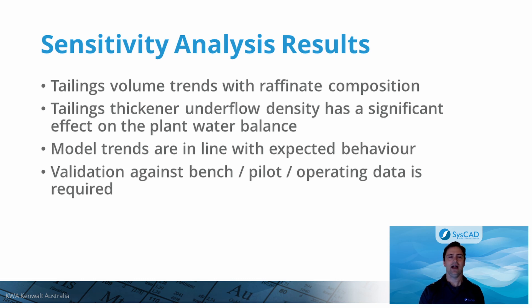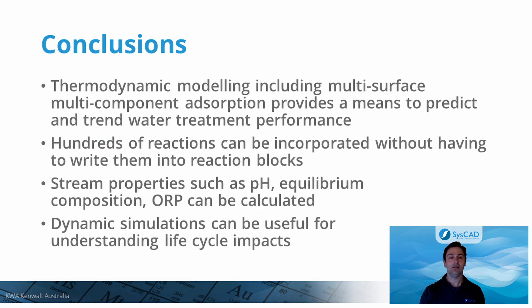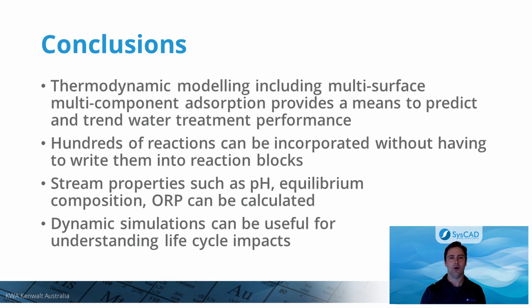This sensitivity analysis also demonstrates how SysCAD with TCE can quantify trending of effluent volume with raffinate concentration as well as run-of-mine tailing solids content. In every scenario tested, model trends were in line with expected behavior. That being said, use of this model or an adaptation of it would require validation against bench, pilot, or operating data prior to use for actual plant design. In conclusion, SysCAD combined with the TCE add-on provides a means to model very complex processes. The PHREEQC software package with an adapted version of the MINTEQ version 4 database was integrated into SysCAD to model the ferric-lime water treatment process. The model comprised 656 species and nearly 30 elements and included solids precipitation and multi-surface multi-component adsorption. This model represented thousands of reactions but was done without having to write any reactions into SysCAD.